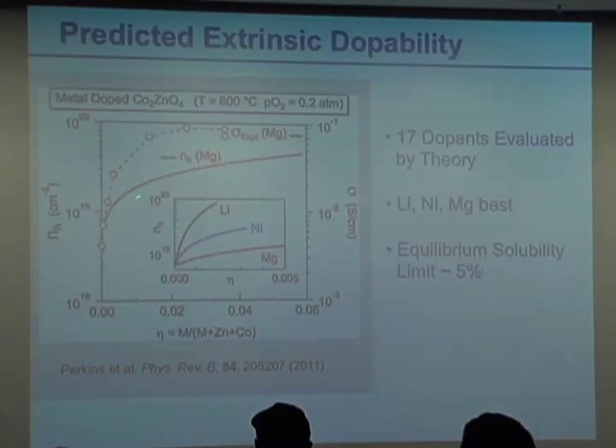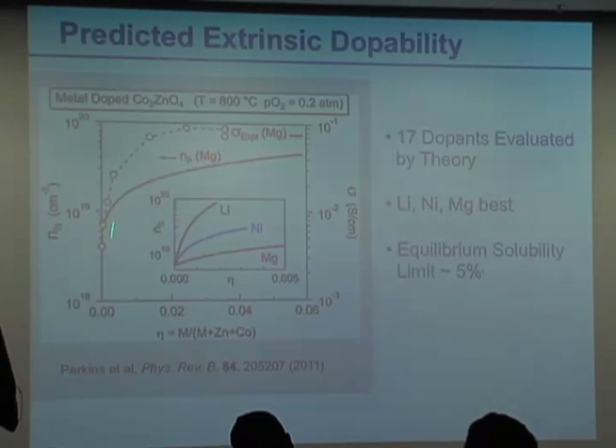And here's our experimental calculation for what magnesium would do at small levels, going where magnesium would go to the tetrahedral site, to the octahedral site. And we see experimentally that magnesium doping gives us a factor of about 5, up to about 5%. We got very interested in looking at the nickel system next.